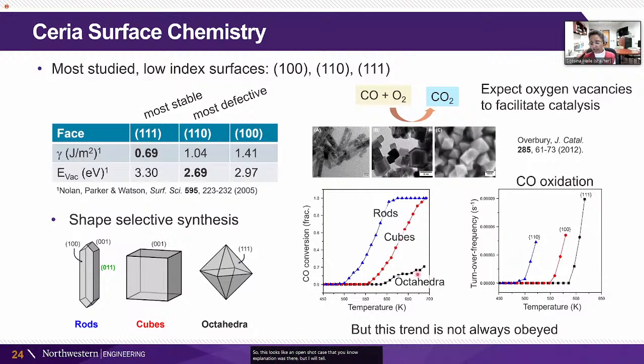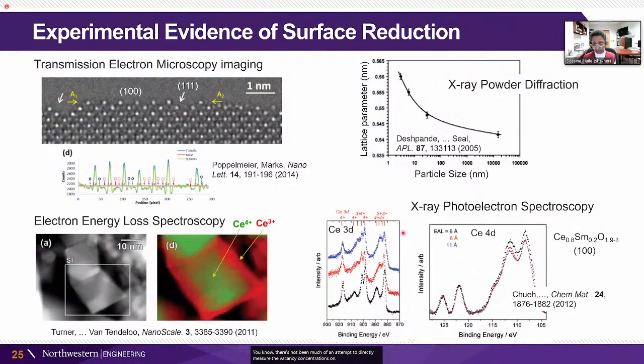But I will tell you that if you look a little bit further in the literature, this trend is not always obeyed. And so it's not clear that this is a universal response. And it's also not clear, there's not been much of an attempt to directly measure the vacancy concentrations on these different surfaces. There have been a few here, and it is well known that the surfaces of Ceria have higher vacancy concentrations than the bulk. What's not clear is how the different terminations vary.